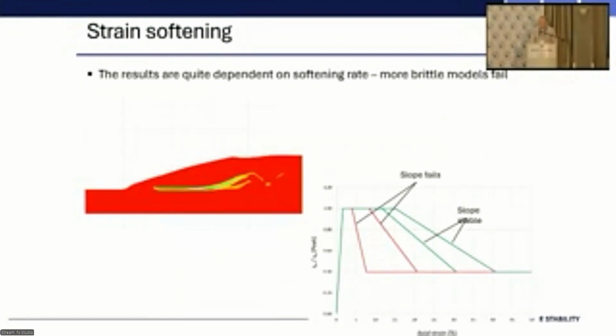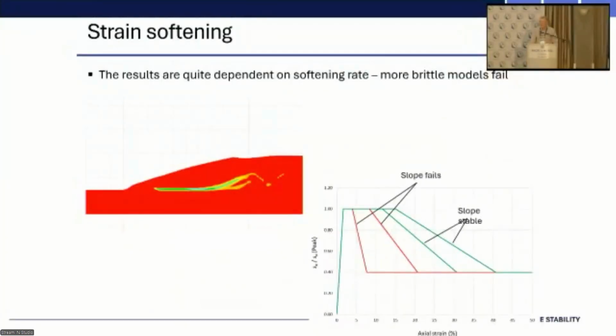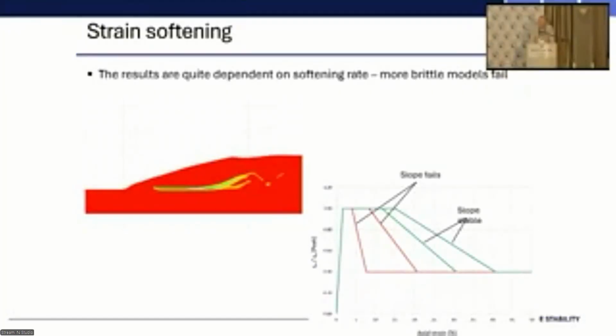And in fact, it becomes very dependent on that rate of loss of strength. So the two left-hand lines on that figure, I'm conscious again of green versus red, that's why I'm not referring to it. But the slope actually failed. And you got full mobilization of strength, you got a kinematic mechanism developed. Whereas the two on the right-hand side that showed the same loss of strength, it didn't fail. Mobilized quite large displacements and had a zone of plasticity developing where the strength was mobilized, but it didn't propagate throughout.